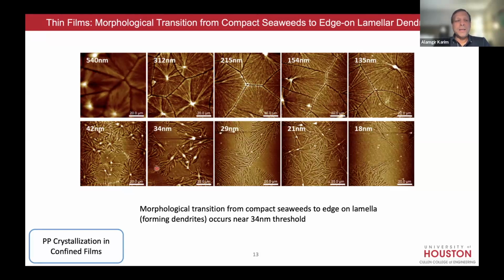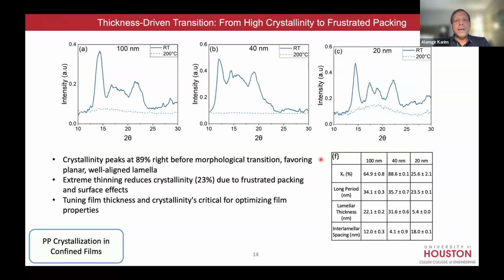And ultimately, below 100, you can see the number of nucleating densities increases. This is interesting in its own right to study. I'll show you just the result, but we can contemplate why it happens. And then ultimately you get fibrils. When you get down to 25, 30, 40 nanometers, you're getting polypropylene fibers because it's not forming a continuous film. All right. We have a technique called GIWAXS that we use at Argonne National Lab Advanced Photon Source.